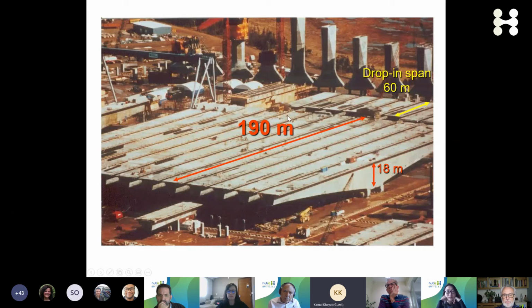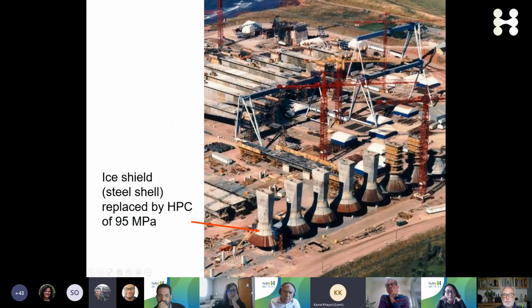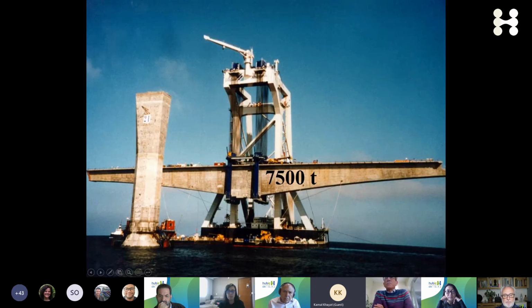And then you have also all the piers, so both sides of piers. In some areas, they use very high strength concrete for abrasion resistance of ice. The gantry that was used for this construction was brought from Denmark and Sweden, where it was used for a link project and was increased in capacity by 25%. And this is the biggest, heaviest marine lift ever, 7,500 tons, to position the precast elements on this bridge.